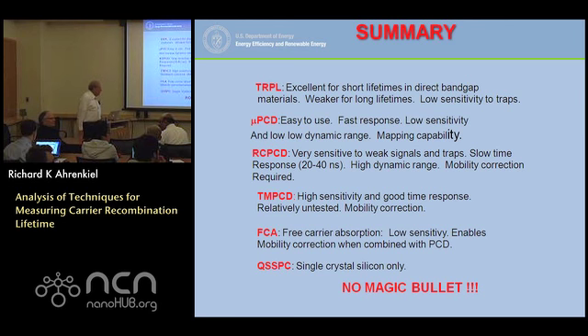Okay, last question. One more question is, for a silicon wafer, you use different wavelengths to detect different lifetimes. So how can I explain that different wavelengths will give you a different lifetime? Okay, what happens is when you use shorter wavelengths, they're absorbed near the surface. You have a Beer's law profile. Maybe at 500 nanometers, the Beer's law absorption length is a micron or something like that. I'm just guessing. So you're putting all the carriers right at the surface. And so initially they see a lot of surface and not a lot of bulk. So the surface sucks them up like crazy, so the lifetime really shortens.